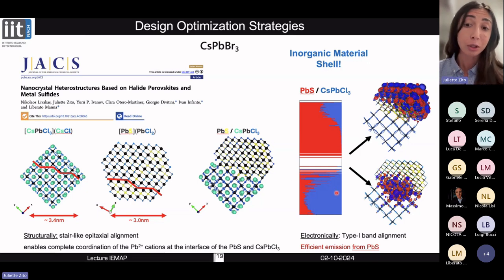And from an electronic point of view, when looking at these interfaced materials, a very important concept is the band alignment between the two materials, because we are looking at two semiconductors. In this case, we found that the lead sulfide material, here in red in the plot, was dominating both the conduction band edge and the valence band edge, so with a type 1 band alignment between the two semiconductors. So the emission in this system was not coming from the perovskite, but rather from the lead sulfide. But this emission was still very efficient because of this favorable epitaxial alignment that allowed healing the surface defects of both sides.